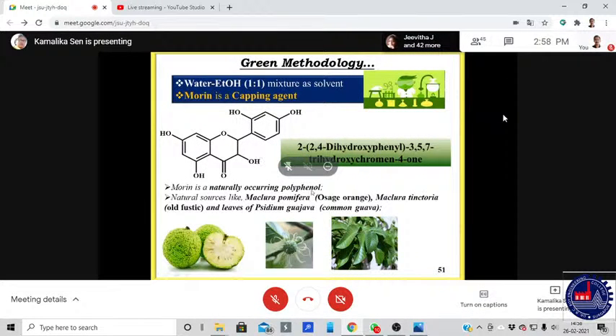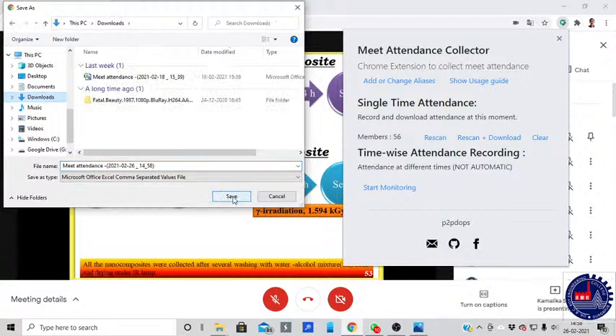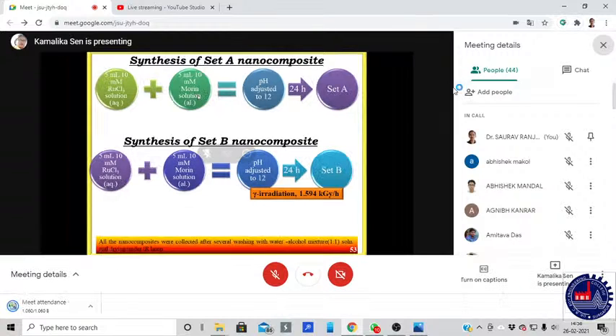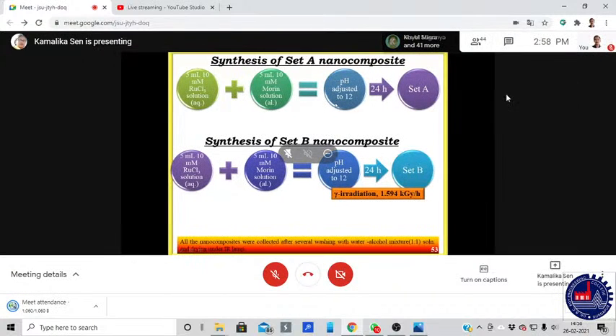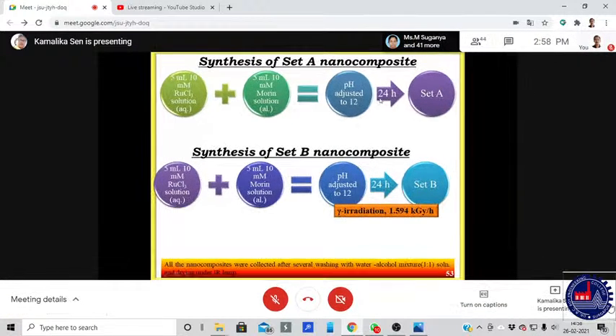It is a naturally occurring polyphenol, and it occurs in the leaves of the common guava, but we have not extracted it from the leaves. We have bought it pure from Sigma, and we have prepared the nanocomposite in absence and in presence of gamma irradiation. We have taken 5 ml of 10 millimolar ruthenium chloride solution and mixed it with 5 ml 10 millimolar Morin solution, adjusted the pH to 12 and settled it for 24 hours.